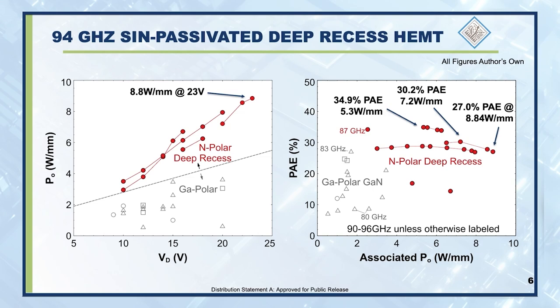Simultaneously, power added efficiency is very important, and we can see that even at 8.84 watts per millimeter, the power added efficiency is very good, 27%. And in fact, at 5.3 watts per millimeter, which in itself is two times higher than what is typically obtained from gallium polar HEMTs, we get a power added efficiency of 35%. This is exceptionally high performance. Power added efficiency is an extreme requirement, because whatever is not produced as RF output power is dissipated as heat, and that requires you to thermally manage the system, which is typically very expensive.